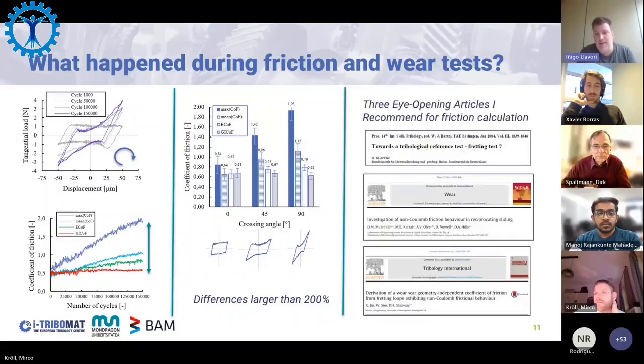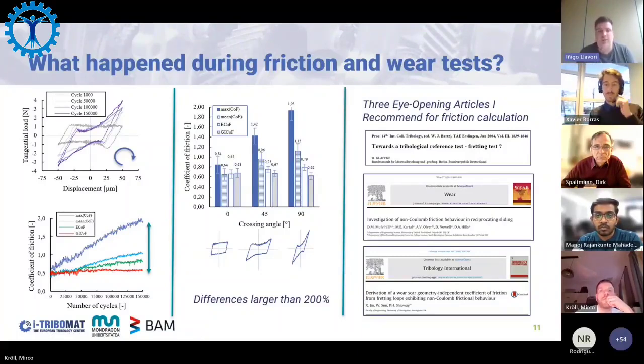So at least from my point of view, I have here 3 eye-opening articles that I recommend for friction calculation. There are more, but from my perspective, these are the 3 papers that I learned a lot from. The first one is from BAM from the early 2000s, and from it I understood the importance of energy, how to calculate the friction energy during the cycle and how to obtain the friction coefficient from that point of view. Then I understood that the distortion of these loops was because of the effect of the wear scar shape, which changed a lot. And depending on how the wear scar is, you have massive differences.